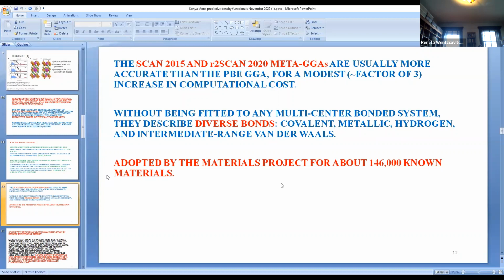These SCAN functionals have been adopted by the Materials Project. The Materials Project is based at Berkeley. It's a website with the computed properties of about 146,000 known materials. All of the known solids for which the crystal structures are known experimentally are in the Materials Project. And their properties have been computed by density functional theory, originally by the PBE-GGA, but the Materials Project is now switching over to SCAN and R2-SCAN. It will take time to do that conversion, but they're doing it.